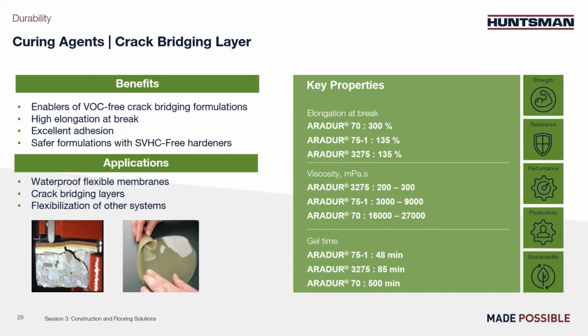Application can be a flexible layer to absorb movement from the ground. And in case of crack, the flexible layer can absorb the crack or the energy of the crack to avoid the propagation to the surface. You can see an example on the picture where the top layer is not damaged while the under part is completely cracked. So more generally, you can create with those products waterproof membrane or flexibilized systems which are a bit too rigid.